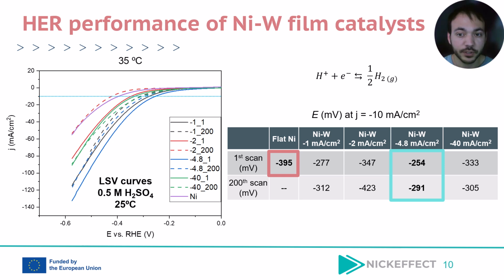Linear sweep voltammetries from 0 towards minus 0.6 volts were performed in 0.5 molar sulfuric acid at 25 degrees, for samples deposited at different current densities. The sample with the best performance at minus 10 mA/cm² during the measurement, both at the first cycle and after 200 cycles, was the sample deposited at minus 4.8 mA/cm².